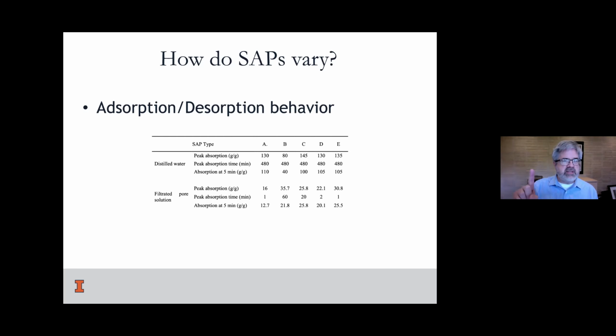The behavior that we see in plain distilled water is not a good measure of what we need to expect in concrete. And furthermore, it's not even a very good predictor. The distilled water, look at this, goes 130 down to 16. Here, a sample goes 80 down to 35. They're just very different. So you might as well just ignore this kind of distilled water test altogether, because it doesn't relate to what we need to do. When we test our SAPs, we need to think about doing this artificial pore solution test.